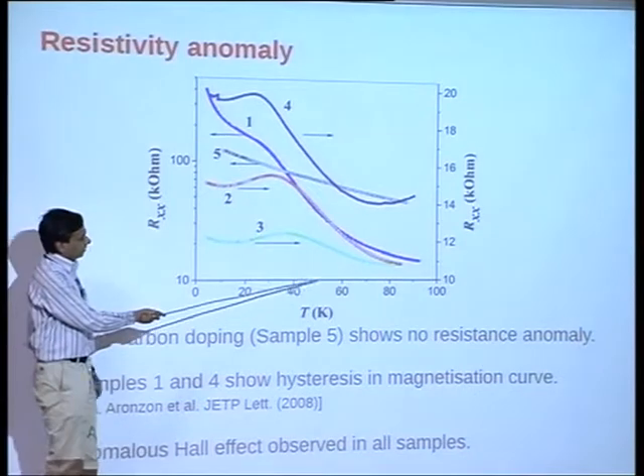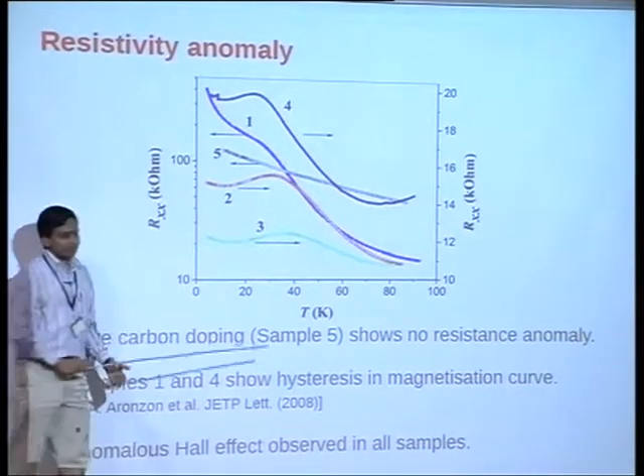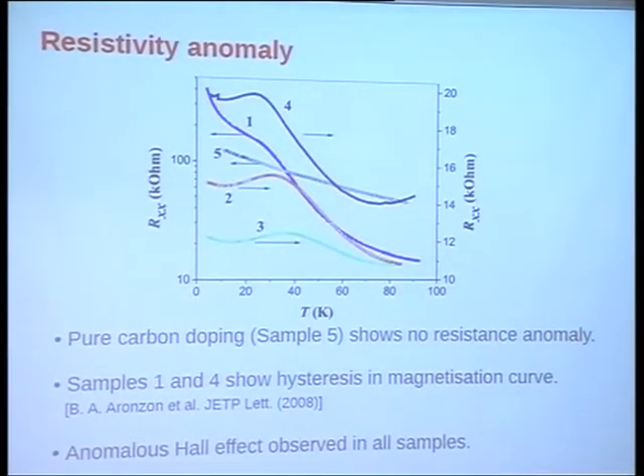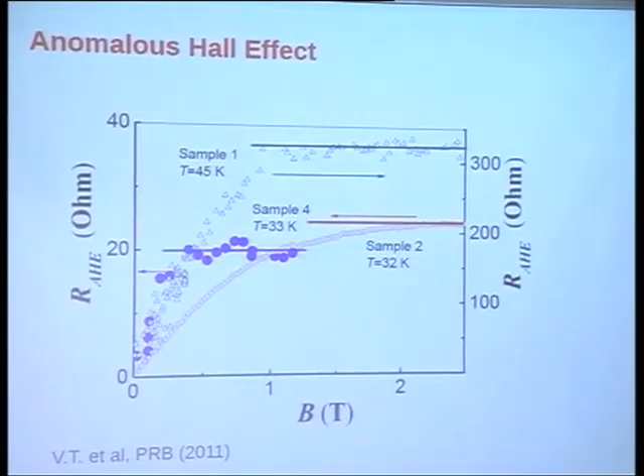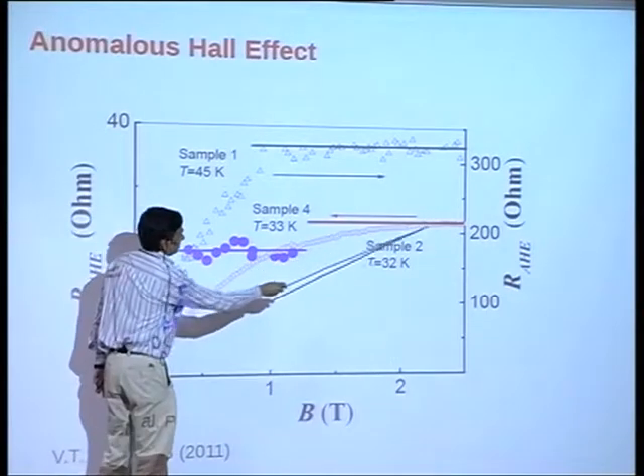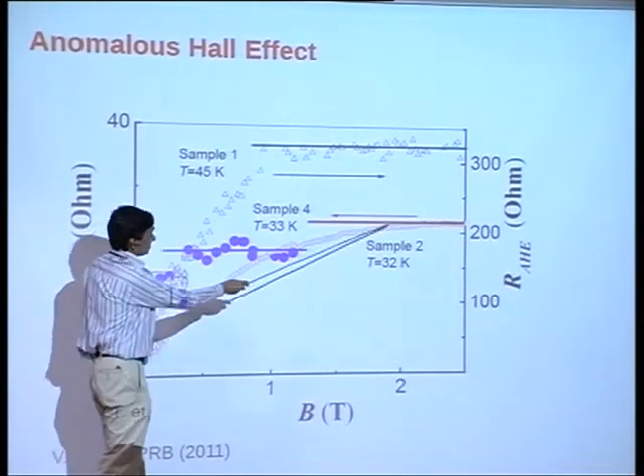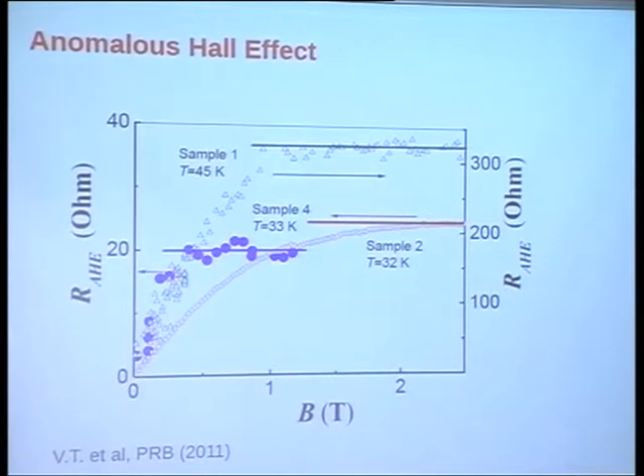We are seeing anomalous Hall effect saturation at much higher temperatures, except in the most metallic sample, where the anomalous Hall effect is still trying to saturate at 32 Kelvins, and presumably hasn't gone ferromagnetic yet.